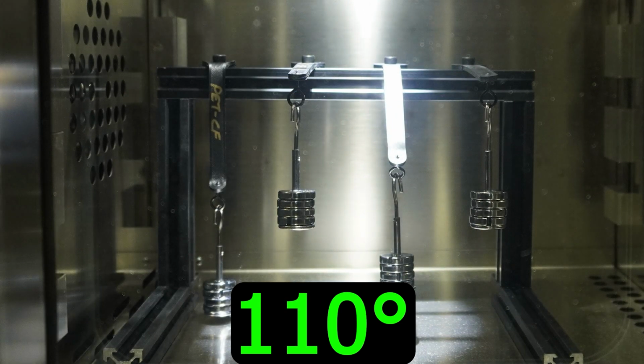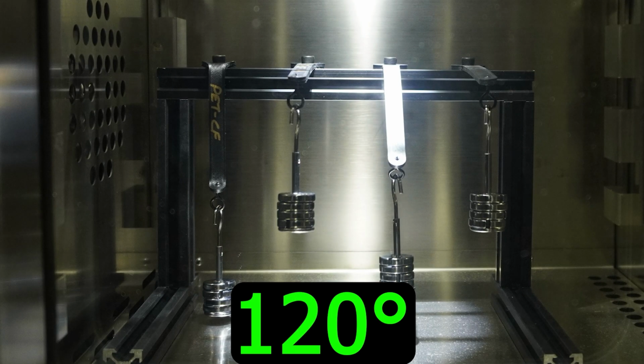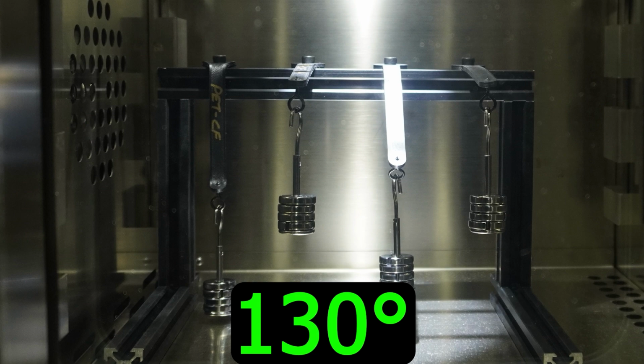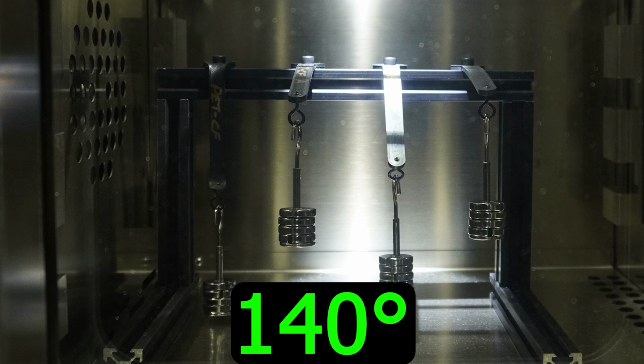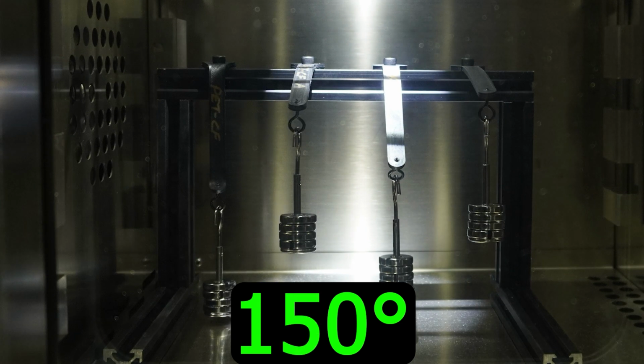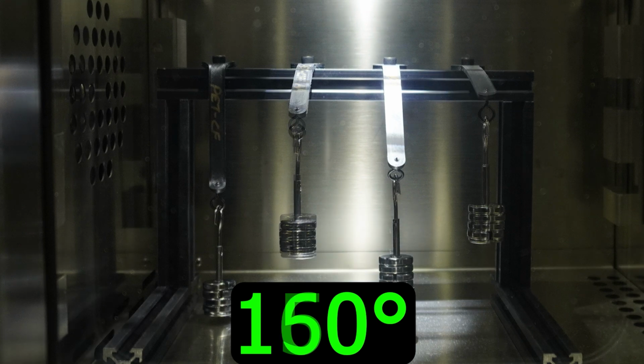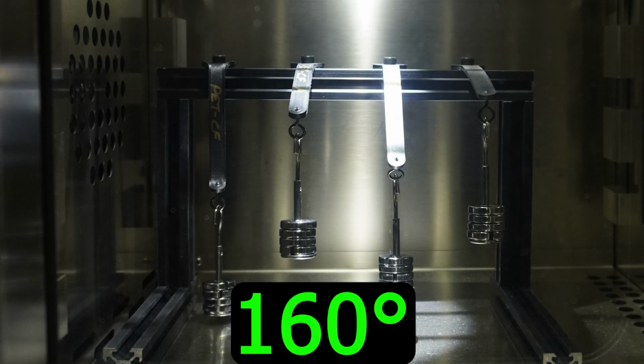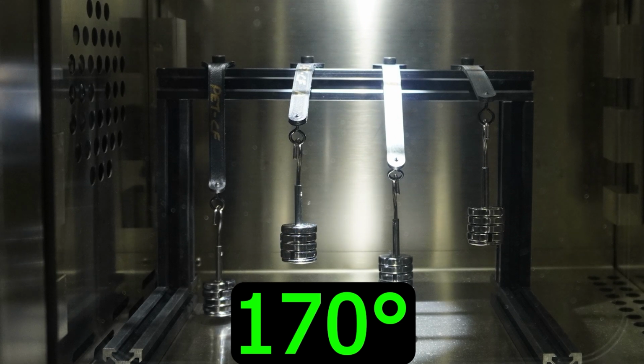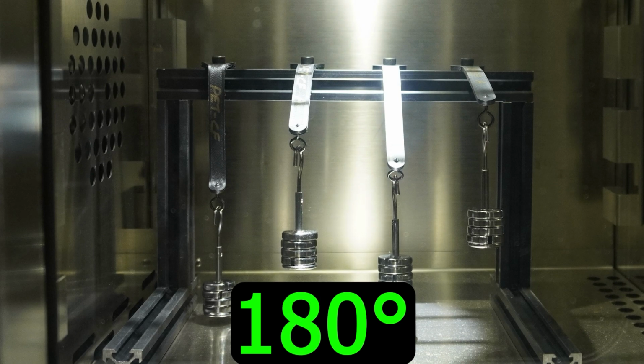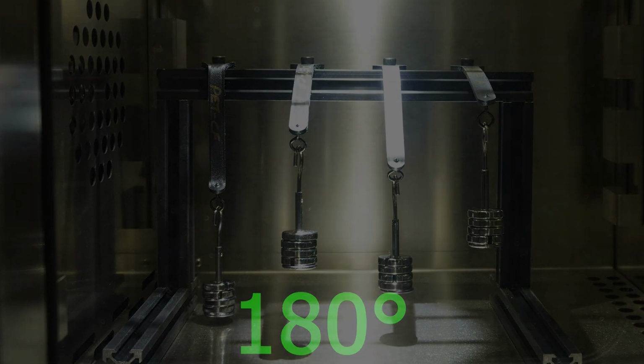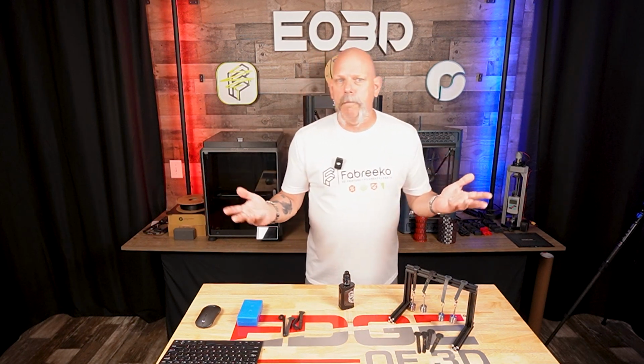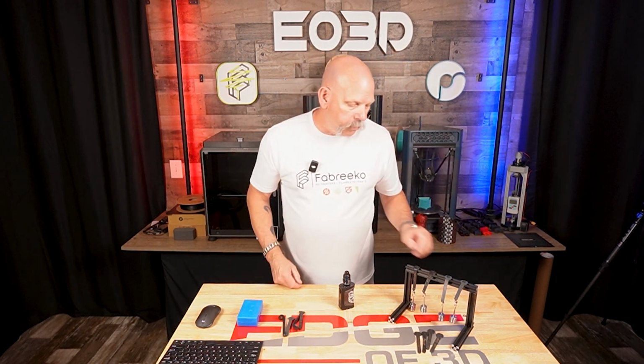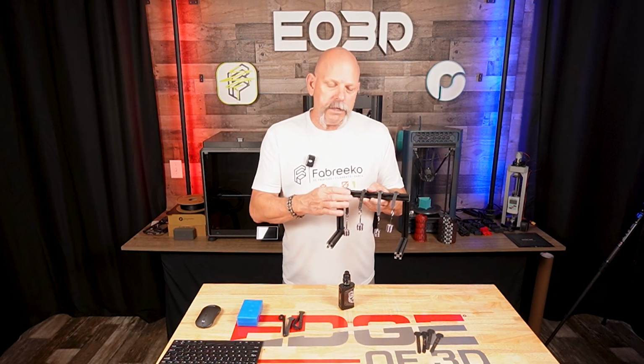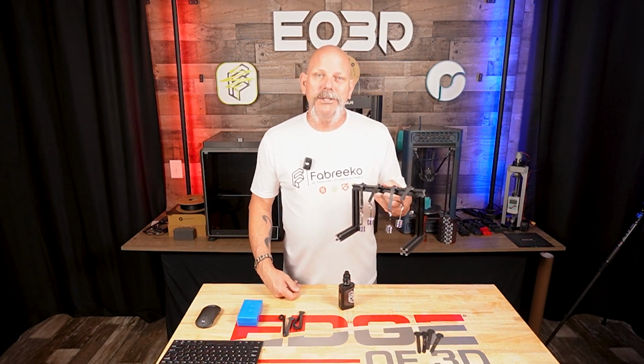At 110 degrees, still no sagging, really anything to be noticed on the PET and the PPS. At 130, 140 degrees, the PET carbon fiber that's annealed really started to sag. The PPS carbon fiber really held in there. 170 degrees, and here's where I cut it off, was at 180 degrees. So you can see from 80 degrees to 180 degrees, well, the unannealed PET carbon fiber, it was done before